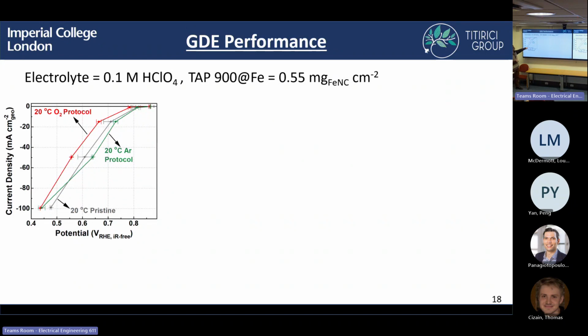And we can see that when we measure the pristine material, after we do the argon protocol, so the argon AST, interestingly, we actually saw a slight improvement in the performance. So we see the potential for the same current density is higher. So that means less overpotential. And this is being proposed to come from the fact that over time, the catalyst surface gets wetter, and so it allows the electrolyte to kind of go deeper within the catalyst layer. So we're proposing that that's probably what's happening during the argon protocol.